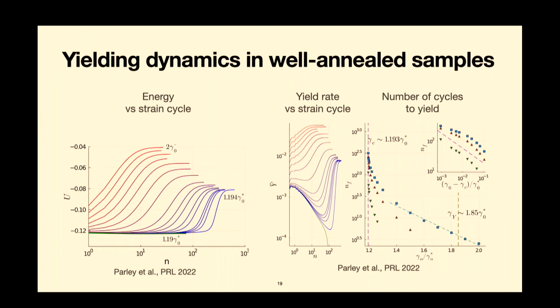You see at high strain amplitudes, this thing is basically 1, so you fluidize almost immediately, and then as you decrease the strain amplitude, you see something that, to a reasonable approximation for a while, looks essentially exponential. That's something that people have used to fit experimental data in these systems: as you lower the amplitude, the number of strain cycles you need until the material yields goes up quite strongly in a roughly exponential fashion. So that applies in this range. Then of course, as you reach our dynamical transition, where the actual steady state changes, this time has to diverge, and if you look at how that divergence happens, it's basically a power law, and we find it's consistent with something that's roughly a square root divergence.